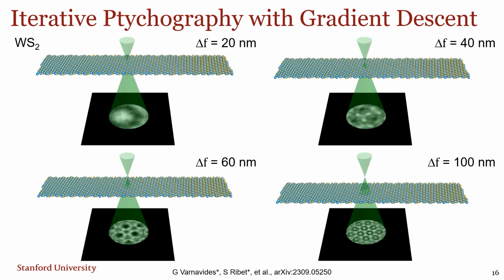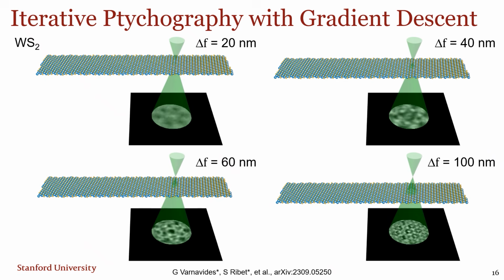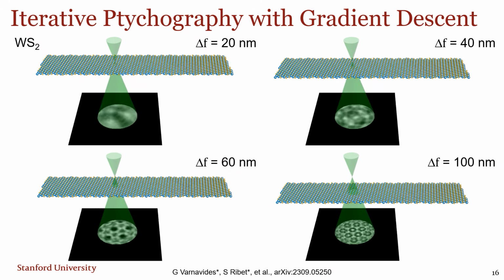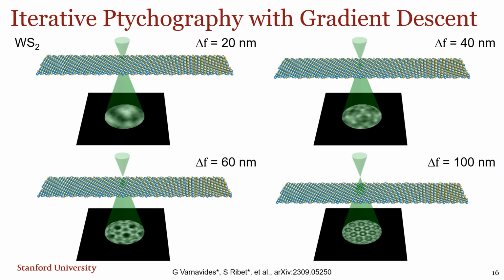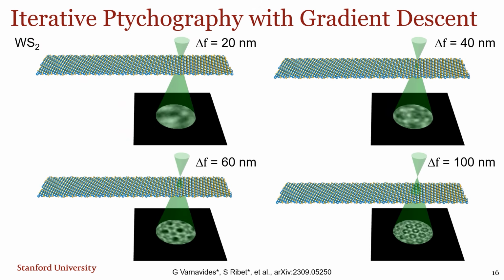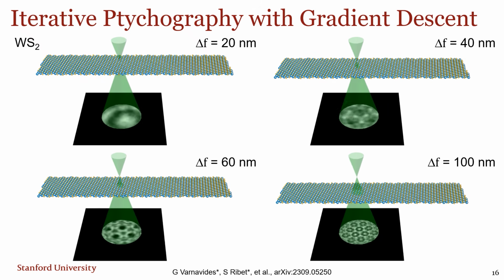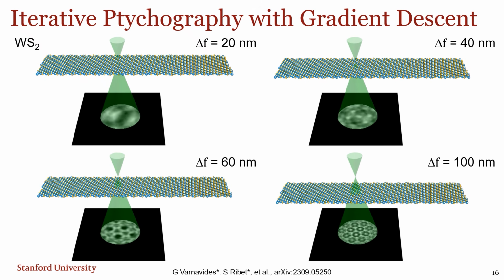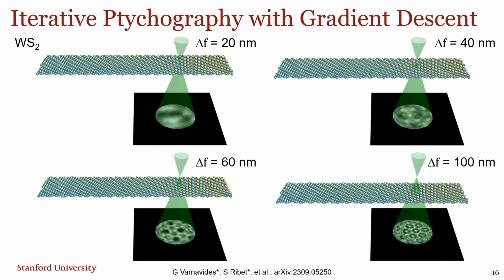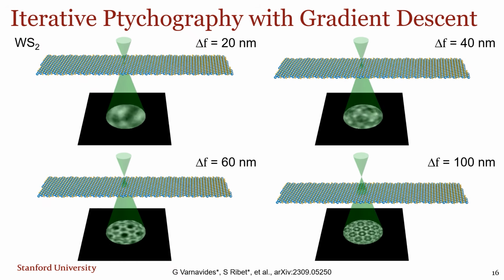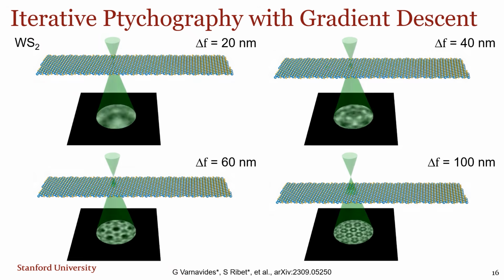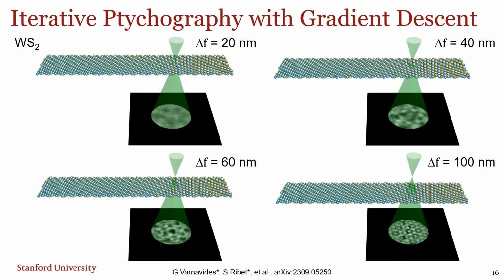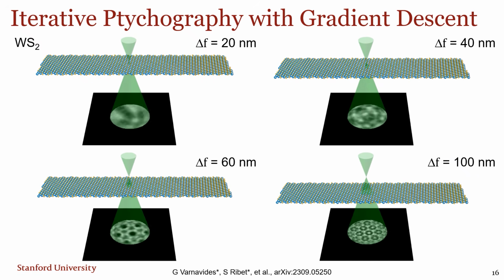So if we were to do that same 4D-STEM experiment here, but on a magnified scale, a much larger convergence semi-angle, this is a simulation showing what it would look like for tungsten disulfide here. And you can see the crystalline hexagonal lattice in what we call the Ronchigram, the far field diffraction pattern of the probe. So what I'm going to show you is how we can use adjacent probes, the overlapping information, to computationally invert the sample structure.